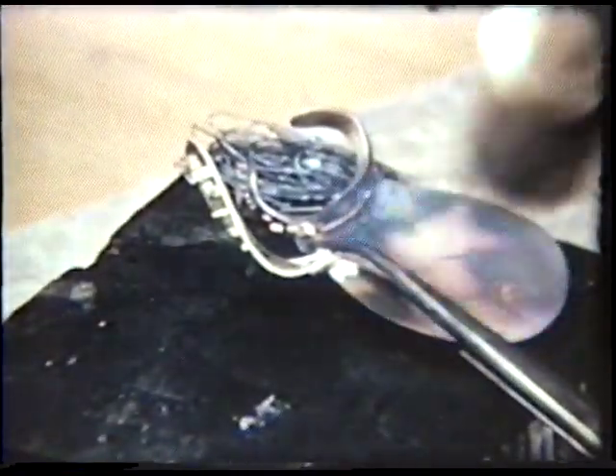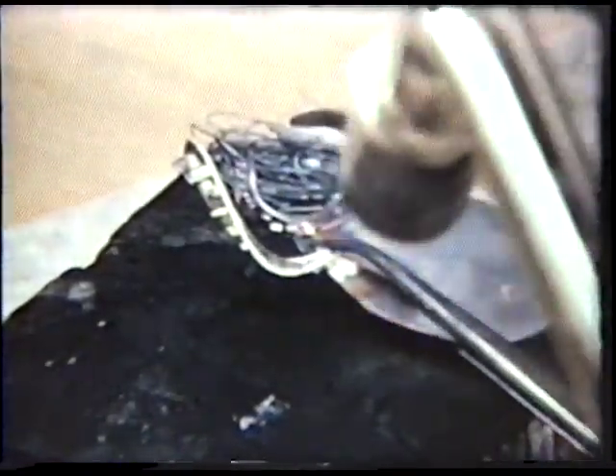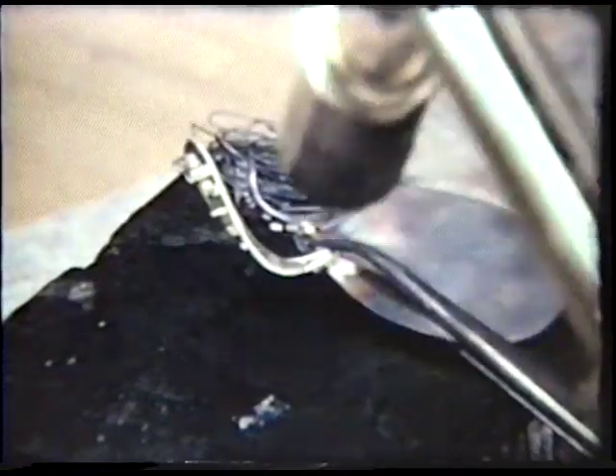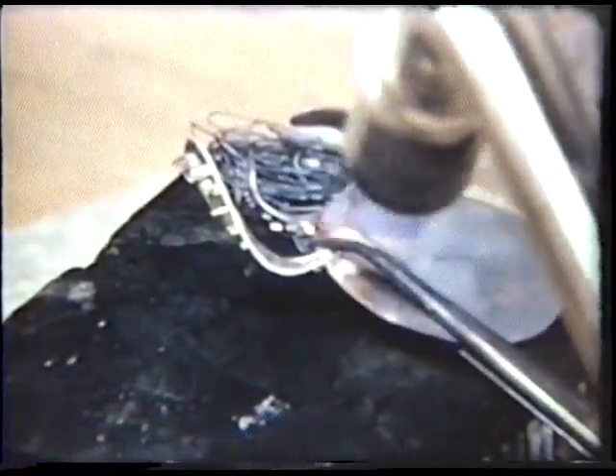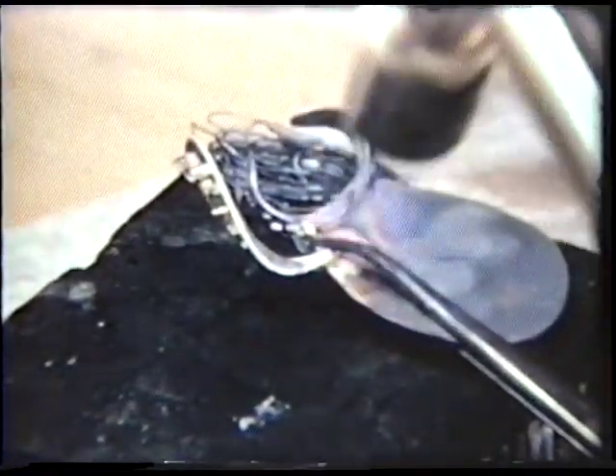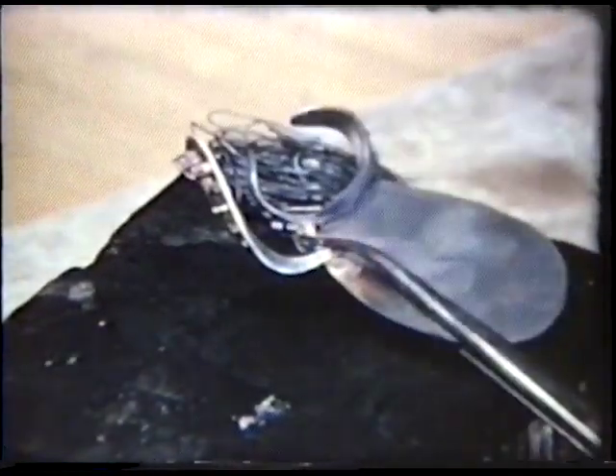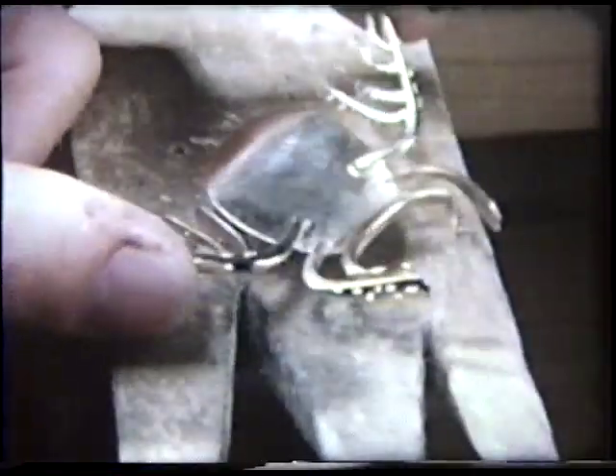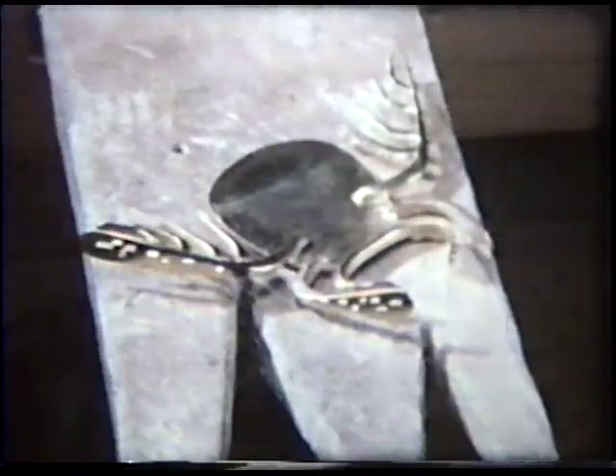The first leg to be soldered is clamped in position with stainless steel tweezers. In soldering, the piece is heated over a large area until the temperature is almost at the flow point of the solder. Then the flame is concentrated at the joint, drawing the solder through it. Each adjacent piece is attached with a lower melting point solder, if possible.